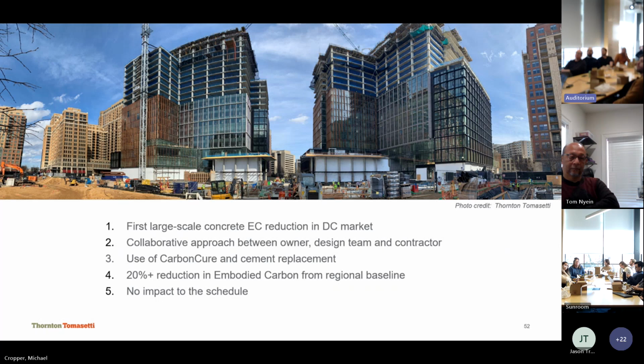Anybody done a post-tension concrete building in the district? Pretty much everybody, because that's what we do a lot of. It used to be, and I saw this all the time, we would get mix designs, right? We spec a 5,000 PSI concrete slab, but it's post-tension, so it needs to get up to strength really quickly so they can stress the tendons and then be able to strip the formwork and do the reshores and keep going.